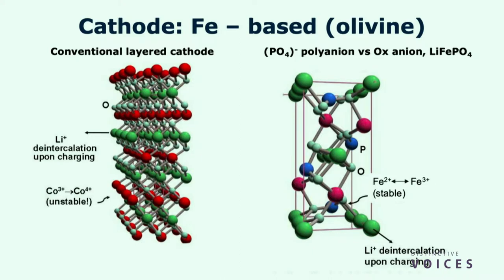If we look at the standard cobalt-based or nickel manganese cobalt layered structures, they rely on cobalt or nickel. There's another problem. If you overcharge a nickel manganese cobalt NMC cathode, it releases oxygen. It generates heat. Not a good thing when you have a combustible liquid electrolyte. That's what causes fires. But if you go to lithium iron phosphate, so instead of using oxygen, you use PO4 as the anion, this is a much more stable bond and it's non-flammable. It never releases oxygen. But most importantly, it's iron-based. It does not rely on cobalt or nickel at all.